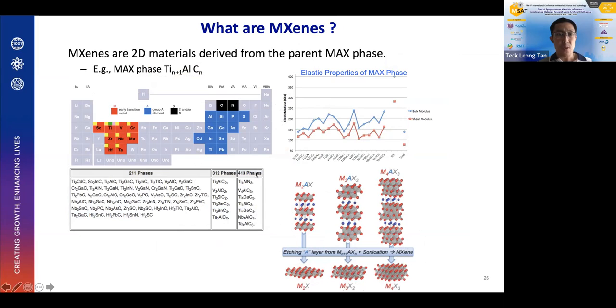Some of us might be familiar with these materials called MAX phase, which is essentially a layered carbide, with transition metal elements and carbon or nitrogen for the non-metals. In the picture on the right, we have the MAX phase, and if we etch out, if we remove these aluminum layers, then we can form these 2D materials, right?